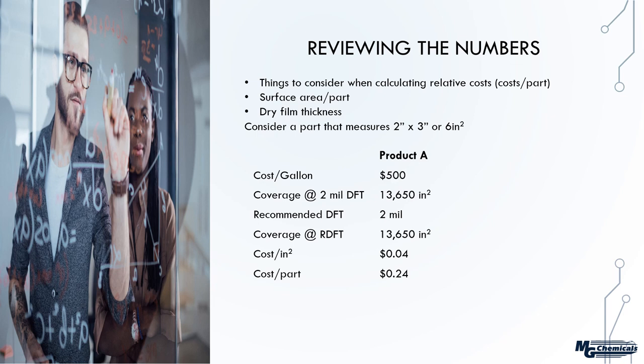So therefore, the coverage at the recommended dry film thickness doesn't change. It's still 13,650. The cost per square inch is simply 500 divided by the coverage, which comes out to 4 cents per square inch. Then you multiply it by the surface area, and you end up with 24 cents per part.